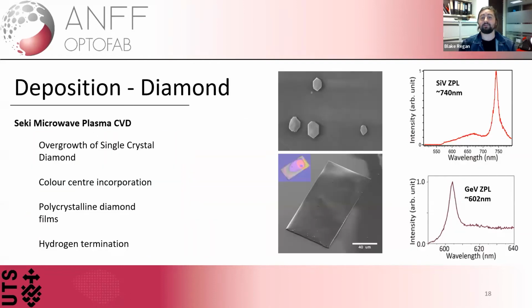I just figured I'd include some images of our deposition of diamond. On the top left-hand side, you see the growth of single crystal nanodiamonds. Now, these ones were specifically grown to include SiV, and I've shown the ZPL, or the emission spectrum, of the SiV nano emitters, which is at around 740 nanometers.